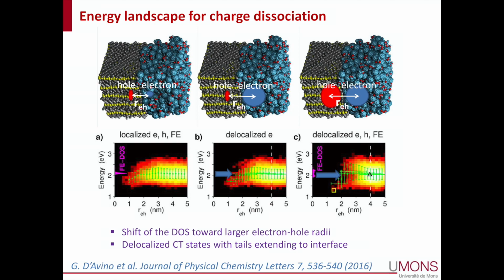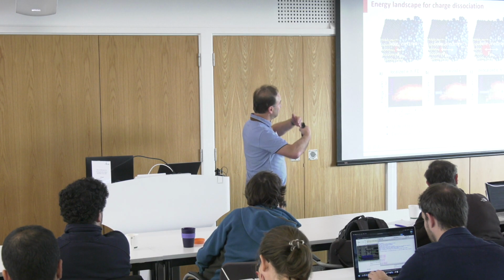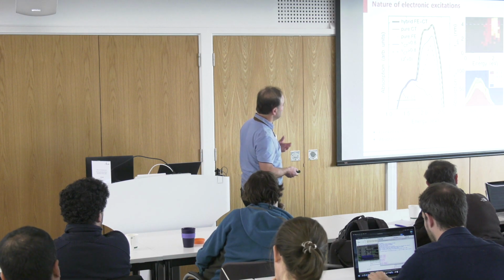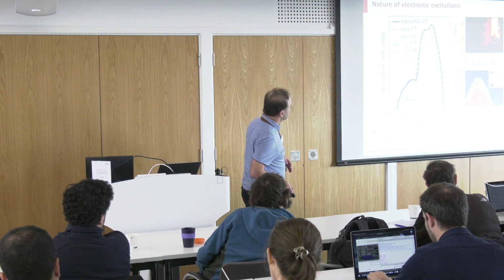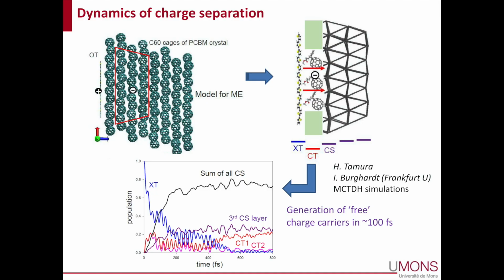So that means that you still get some lower energy states, but on average, you tend to favor states with delocalized hole and electron wave functions tailing towards the interface. This is important for the exciton dissociation process that turns out to be extremely fast in those structures with large energy offset. And this is because we are creating at the interface delocalized states with tails towards the interface.